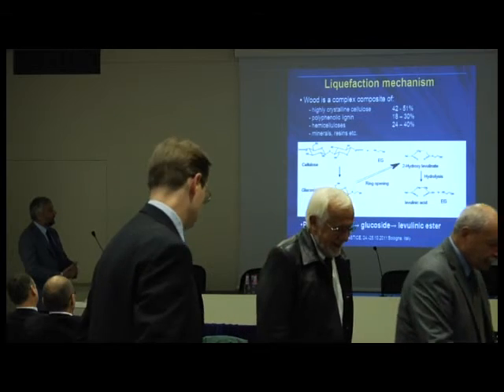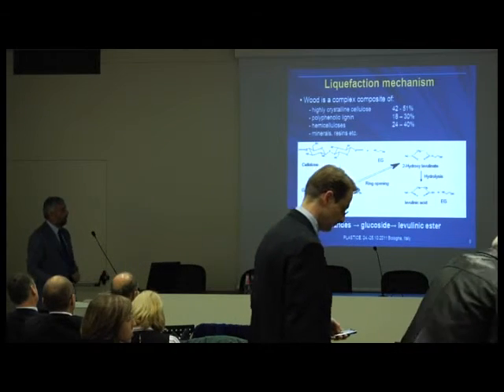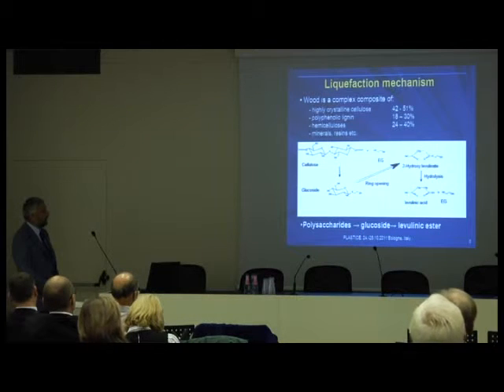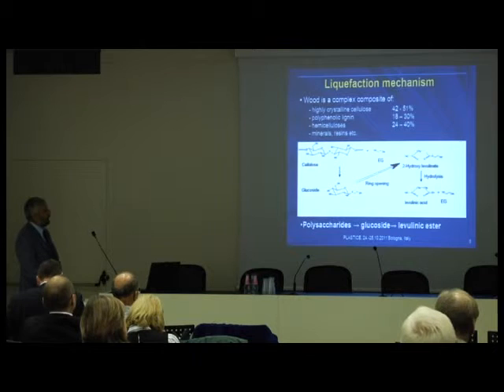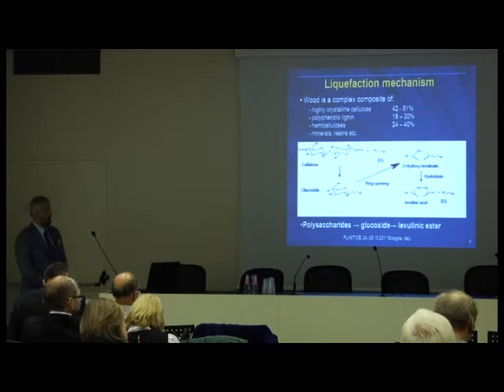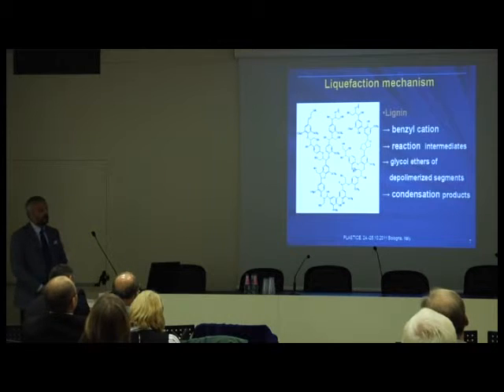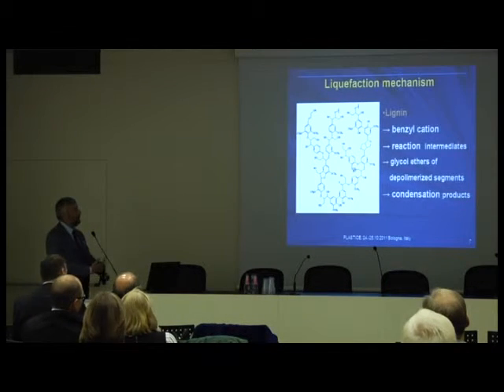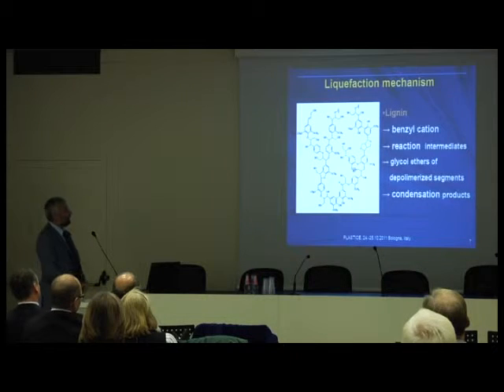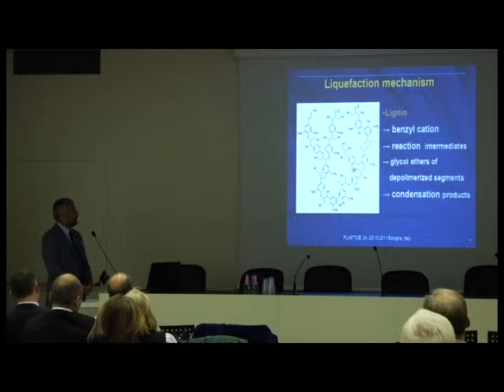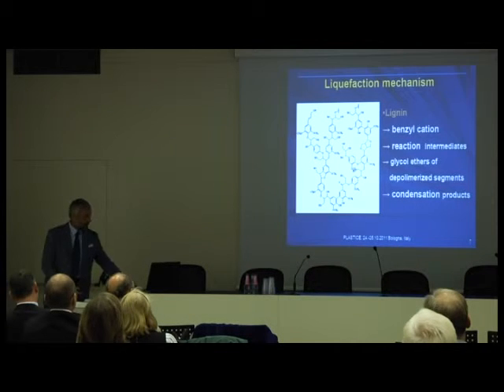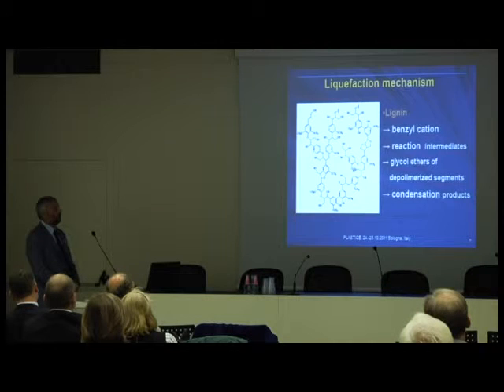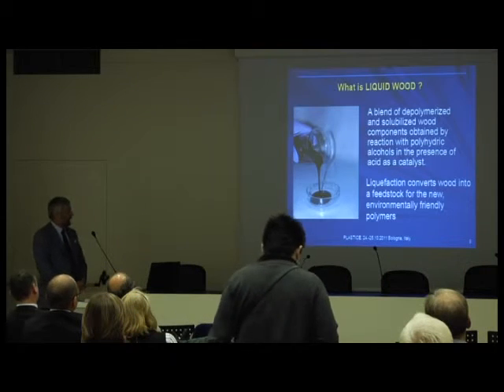Here the main point is that you simply depolymerize this cellulosic chain into more monomeric or oligomeric parts, and here you use some glycols to do that, and acid is used as a catalyst. The situation with lignin is more complicated. Again, you depolymerize the very complex lignin polymer into simpler units, and of course, again, we use these glycols in this process. And I would say that here we still don't know exactly what is going on during the liquefaction process.